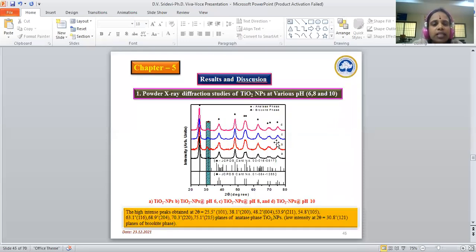This slide shows the powder X-ray diffraction studies of TiO2 nanoparticles at various pH levels. The high intensity peaks at 2 theta values 25.5, 38, 48.2, 53.9, 54.8, 63.1, 68.9, 70.3, 75.1 correspond to the tetragonal anatase phase of TiO2 nanoparticles. Likewise, the low intensity peak at 2 theta value of 30.8, with the corresponding plane of 121, shows the orthorhombic brookite phase. As a result, the as synthesized nanoparticles show a highly crystalline anatase phase with a small amount of brookite phase.